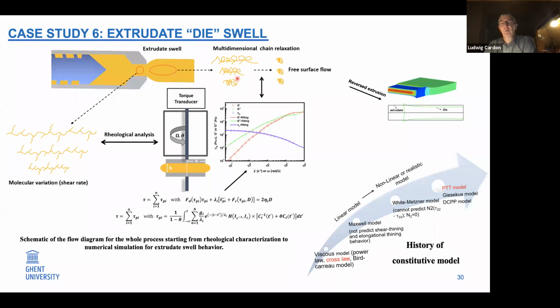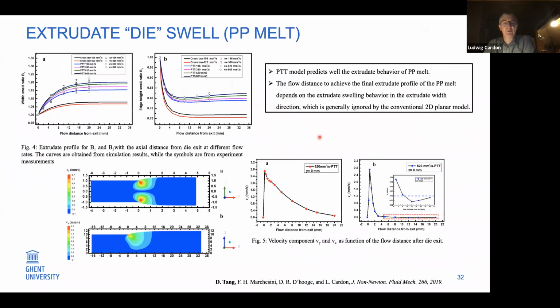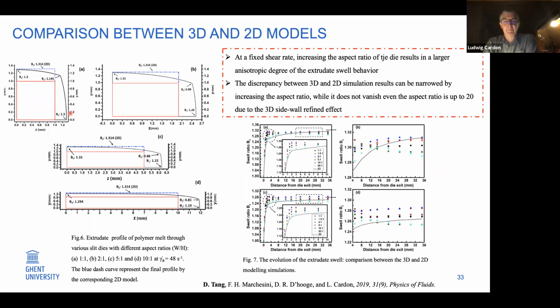So that's what we also try to investigate, the effect of the compression, the shear effects inside materials. This was investigated using constitutive models, by using the standard Cross-Sloban Maxwell and also the PTT model. What we find out, I go to the next slide to showcase, is that mimicking the whole process was rather optimal taking in mind the so-called PTT model, in which you try to mimic the effect of the die swell based on polypropylene. Okay, so you can read all the details also, for instance, in the journal Physics of Fluids, in which we compared